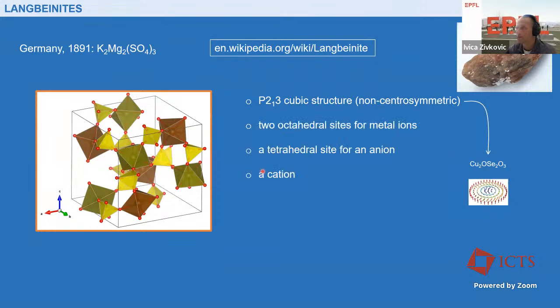The other characteristic features of the structure are that there are 2 octahedral sites which contain metal ions. So you can see them here. The octahedra are not perfect, but they are almost perfect. There is a slight rhombohedral distortion from the ideal dimensions. Then you have sulfates coordinated with 4 oxygens, so that forms a tetrahedron. And basically, this is where your interaction comes through. And then there is a cation, in this case potassium, which is removed from this picture.